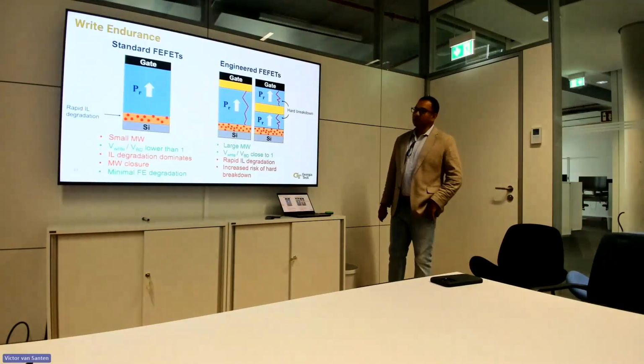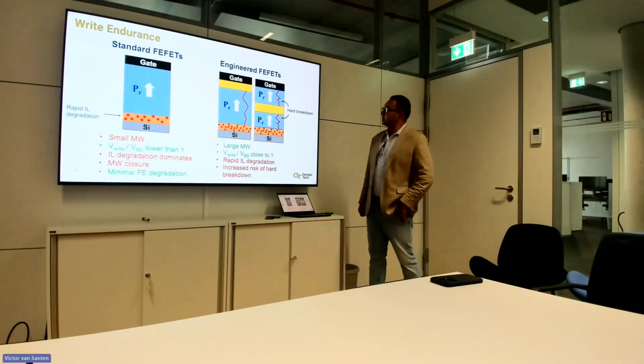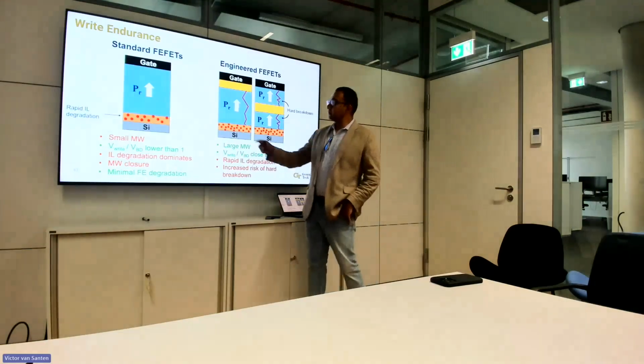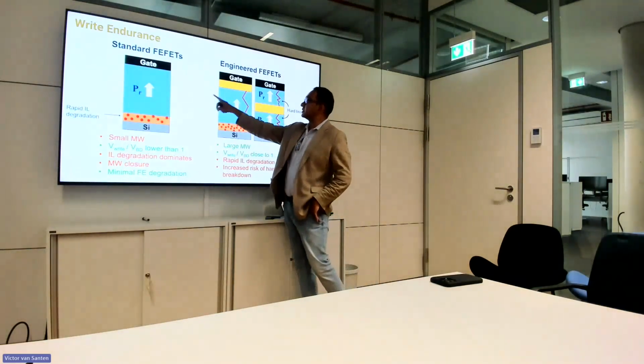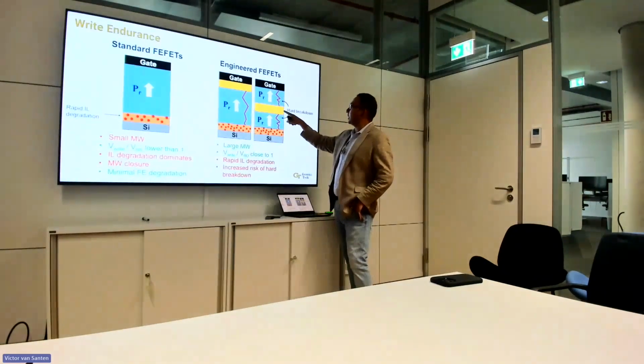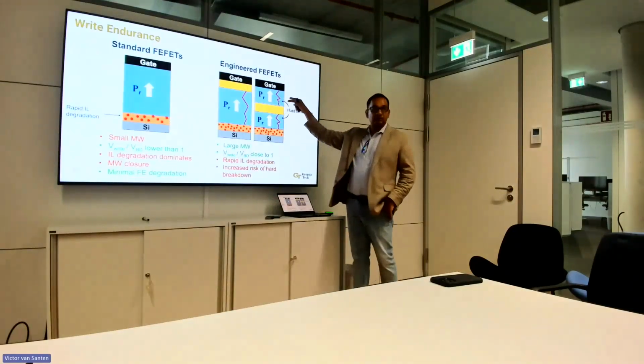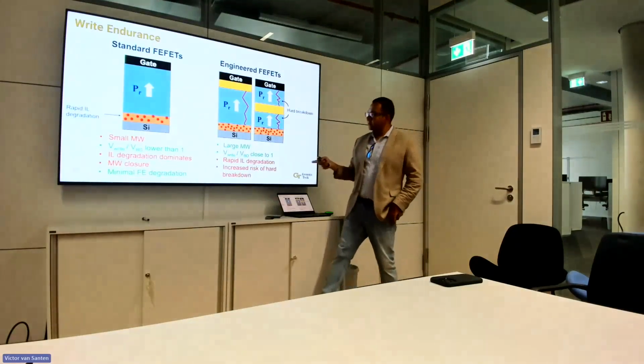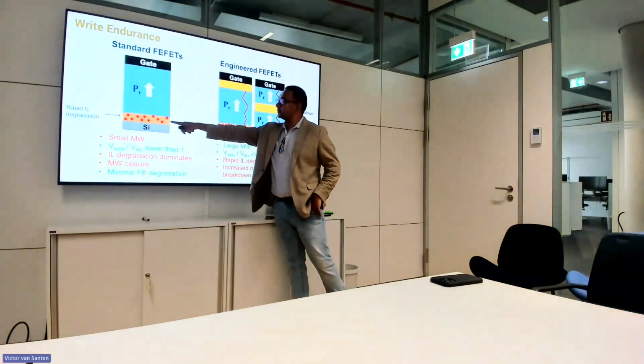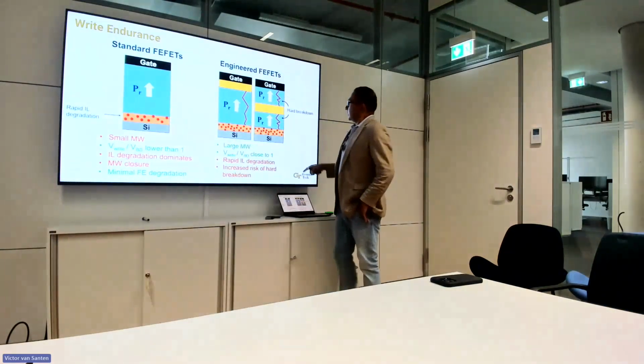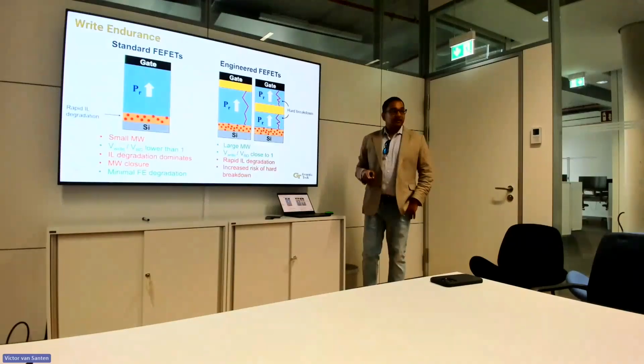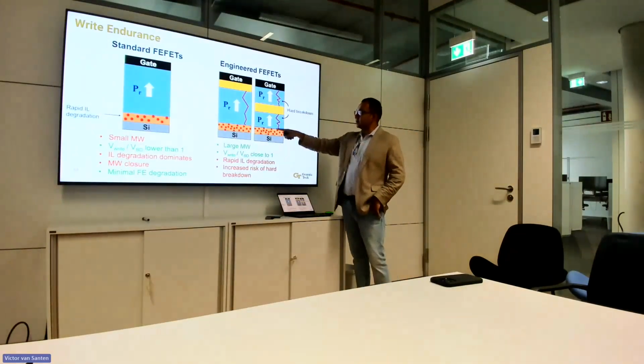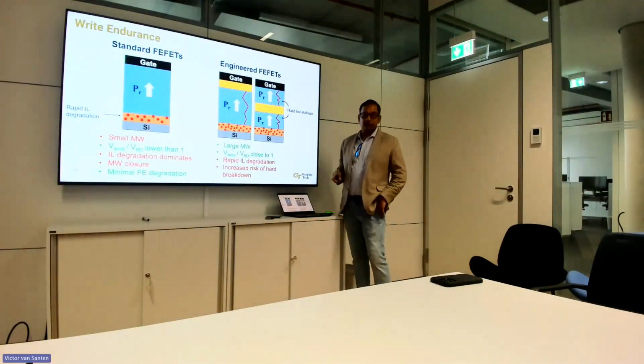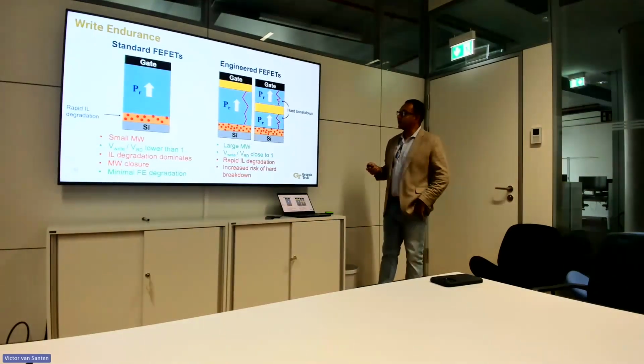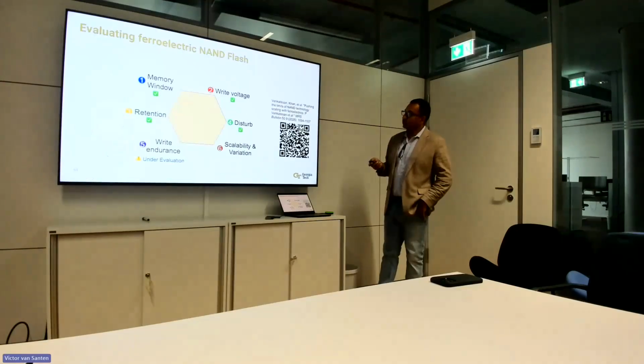And I'll not go into the details, but the mechanism for breakdown for a standard ferroelectric field effect transistor versus one where we have a dielectric in between with a large memory window is actually different. In the standard case, what breaks down is the IL. In this case, what we think breaks down first is the ferroelectric, not the IL. Okay. So this is what we think. Happy to discuss more. Yeah, so that's that.